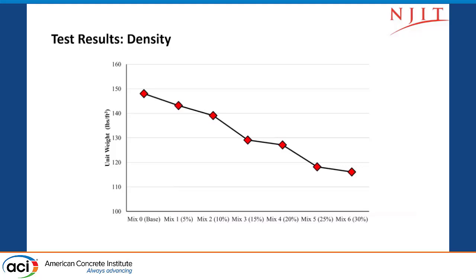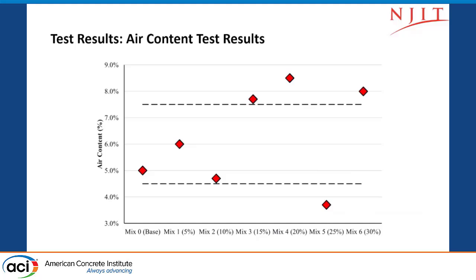The density, as we heard before, the biochar is a porous material, so we are expecting the density is going to go down from 150 to about 117, 118 when we increase the fine aggregate biochar replacement to 30%. This is the air content, and I see two anomalous points, but we are expecting the air content to increase by increasing the replacement for the fine aggregate because of the voids. The voids are more, so we are increasing the air content in the specimen.